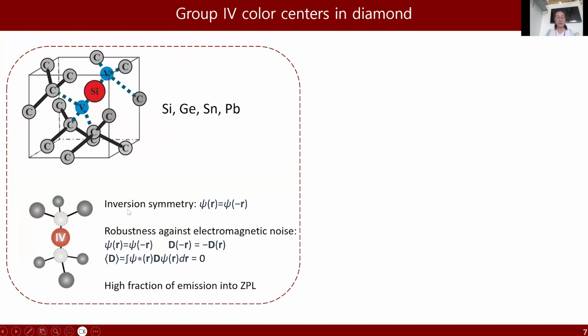And because of this inversion symmetry, those group 4 color centers do not have a permanent dipole, which makes them very robust against electromagnetic noise. So they can be put very close to the diamond surface while still maintaining very good optical coherence. Besides that, they have a very high fraction of emission into the zero phonon line, the direct photon transition without coupling with phonons.